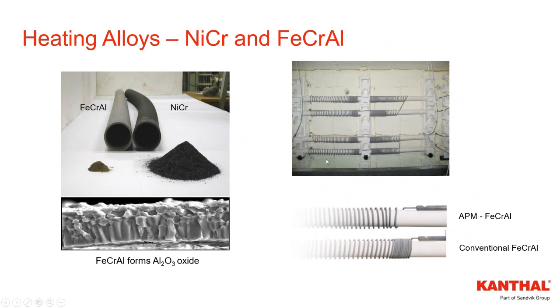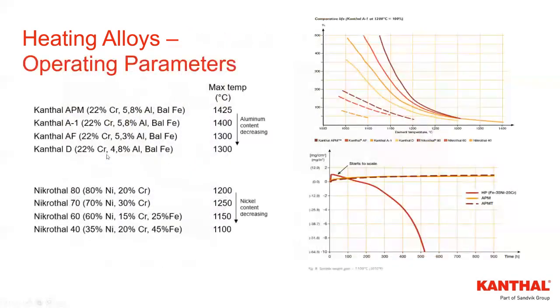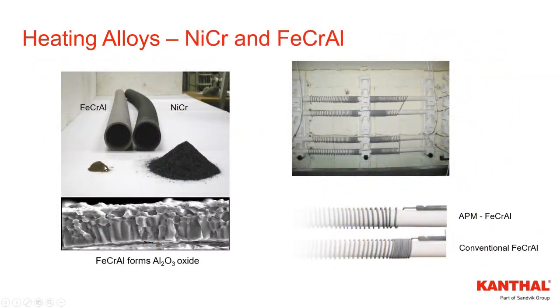What happens with a material that has a thicker oxide that tends to spall off more, which is like a nickel chrome, you're going to consume more of the base material. So in this case, iron chrome aluminum has an aluminum oxide or alumina oxide. So you're going to spall off aluminum, and you're going to consume aluminum in the base material. And then with a nickel chrome, it's a chromium oxide, so you're going to consume chrome.